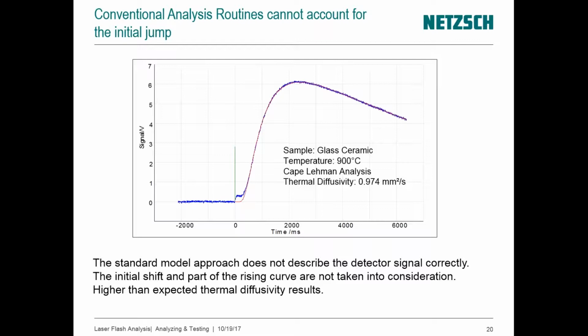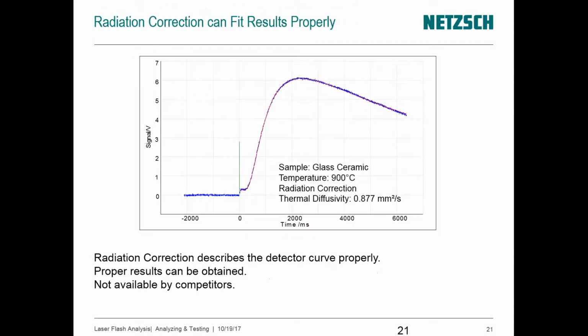But this small energy jump at the beginning is actually due to radiation, or partial radiation, within the specimen. If this was not accounted for, you will tend to measure a diffusivity, in that case 0.974 millimeter square per second. We will see that when the radiation component is accounted for, the actual diffusivity due to conduction is much smaller, close to what is expected. That's what we show here when we use the appropriate model, accounting for radiation through the specimen. We were using a glassy ceramic, of which we knew the thermal diffusivity at 900 degrees, and what we get here, 0.877, is exactly what is expected.